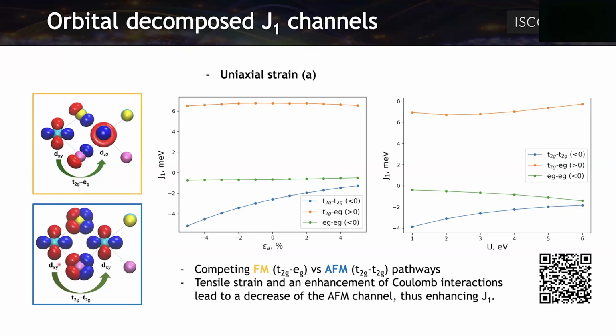Whereas we have this antiferromagnetic interaction between the dxy orbitals, t2g, t2g, because in this case we have already filled them with 3 spin up, one in each one of the t2g orbitals, and the hopping can only go antiferromagnetic. When we are expanding the material along these directions, we are decreasing this antiferromagnetic interaction. And this is the main effect, because we can observe here that the other mechanism, the t2g-eg, is almost constant. So the enhancement of J1 comes from this mechanism that we're reducing when we are pushing these two chromium atoms apart.